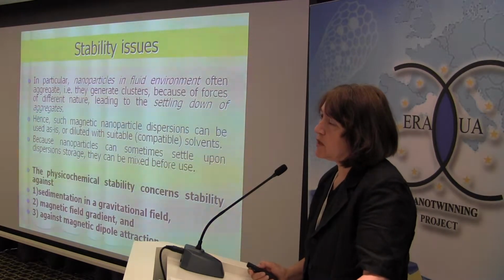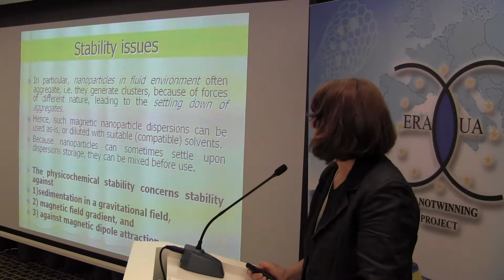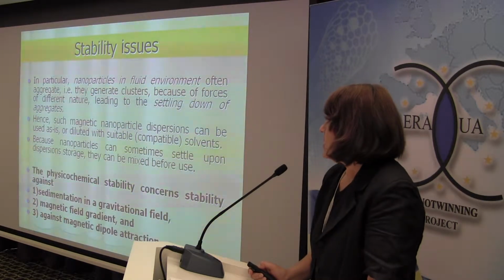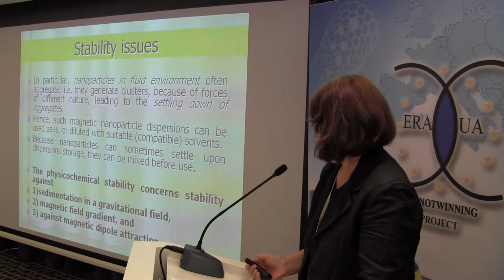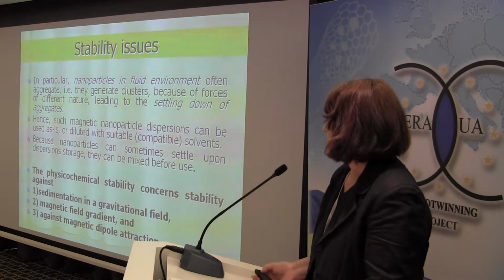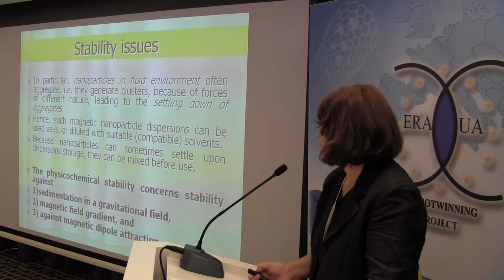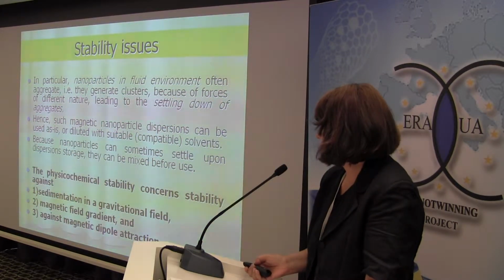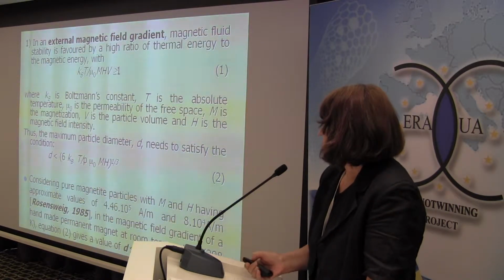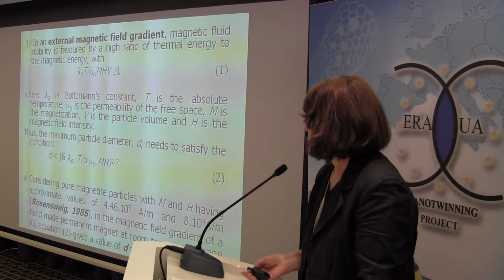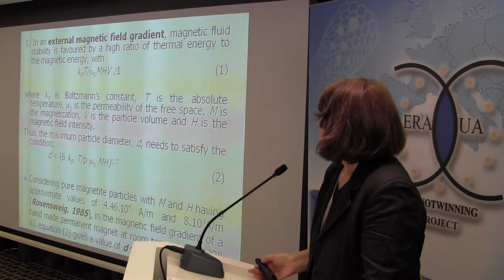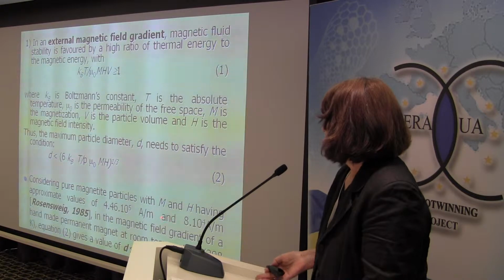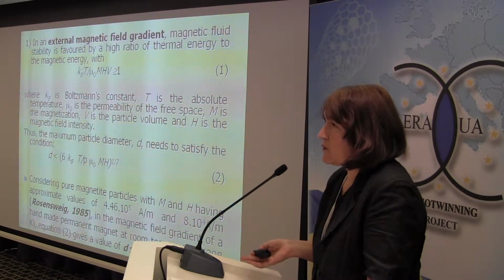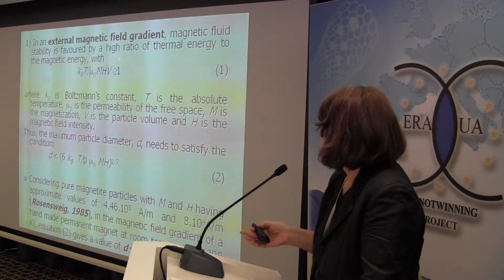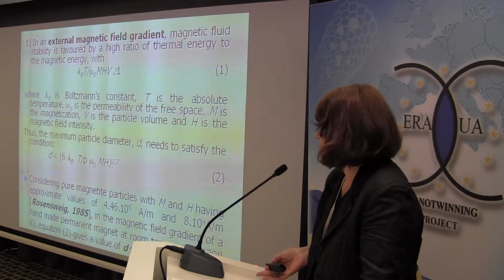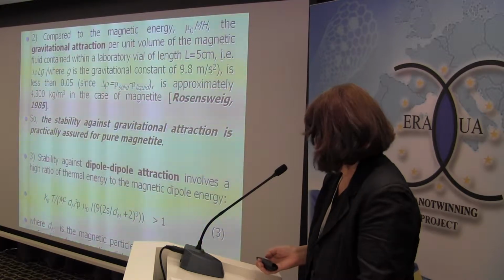So the issues of stability of such soft magnetic materials, like the magnetic nanoparticle suspensions, are dealing with the three main aspects that are mentioned here: the stability in a magnetic field gradient within the gravitational field, and the stability against magnetic dipole-dipole attraction. As the theory is telling us, and as summarized by Rosensweig, the father of magnetic fluids, the main condition that was formulated from theory for the diameter of the magnetic nanoparticle regarding the stability in magnetic field gradient first is that such a diameter remain smaller than 8 nanometer.